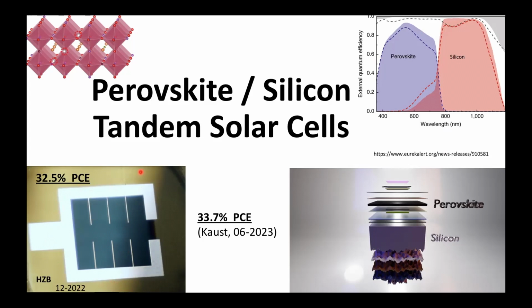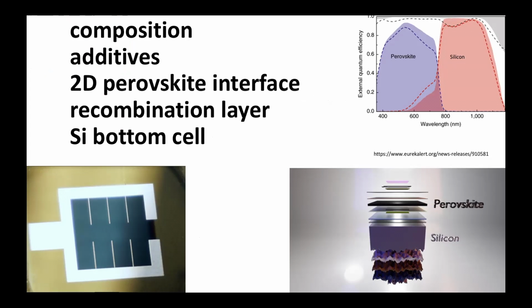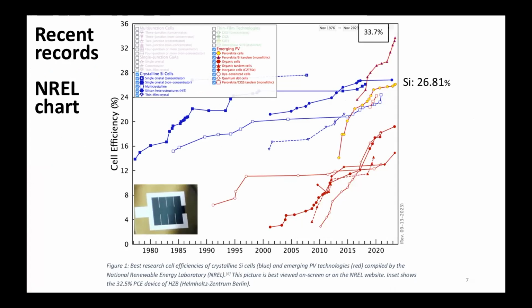You also see that it is a very complex material. The silicon layer is extremely thick relative to the other components. You have all kinds of very, very thin layers, less than 100 nanometers. The perovskite here, and they form a stack with different components, with different functions. So we can discuss the composition, what perovskite is ideal, additives, we have the 2D perovskite interface, and a recombination layer. You have to use it.